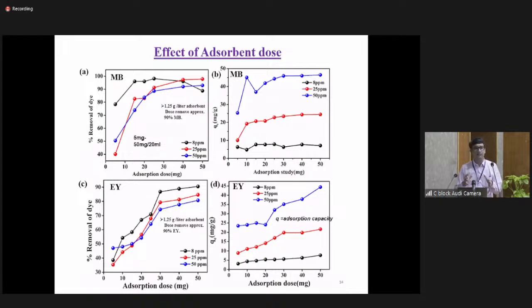Then a study of the effect of adsorbent dosage was carried out. Adsorbent dosage means we use different doses, and the adsorbent here is activated carbon. You add 5 milligram in 20 ml up to 50 milligram in 20 ml, and then we plot the percentage removal of dye for different dye concentrations of 8 ppm, 25 ppm, and 50 ppm. You can see what is happening as the adsorbent dose increases up to a certain level. A dose of 1.25 gram per liter removes around 90% of methylene blue, as you see from the first graph. So you need 1.25 gram per liter of adsorbent to remove 90% of methylene blue. So, not going into too much detail.